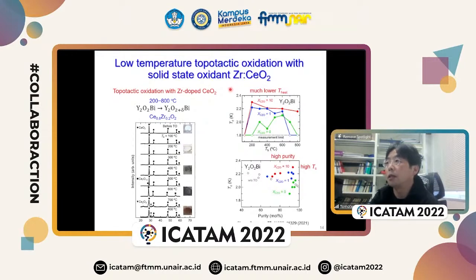We use this zirconia-doped cerium oxide as a solid-state oxidant. We place this compound and this compound separately in the same quartz tube, and we heat them in the quartz tube. This is an XRD pattern of this compound and a picture of this zirconia-doped cerium oxide.